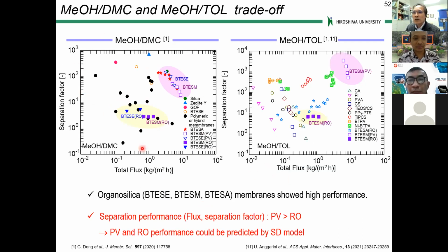Now this slide summarizes the trade-off of the methanol DMC and the methanol toluene trade-off in terms of this reverse osmosis, and then this part, the pink part is PV, okay? With other membranes like silica, zeolite, ZIF type membranes, in most of the membranes, all of the other membranes are just pervaporation, okay? As you can see, organosilica membranes show very high performance, better than other types of membranes. Also, these reverse osmosis and pervaporation were successfully predicted by the solution diffusion model.